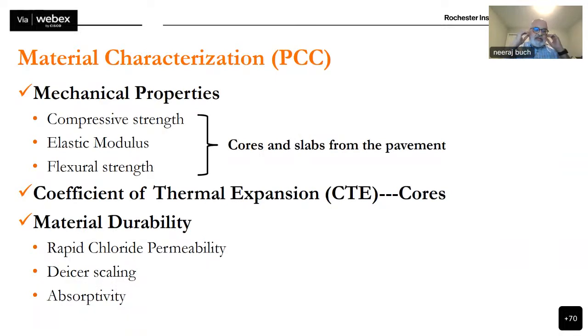So moving on to the material characterization, of course, there were a lot of tests done, and I don't have time to go through all the testing, but I've sort of picked some examples. So we looked at mechanical properties, and the three common mechanical properties that we looked at were the compressive strength, that was either based on cylinders or cores that were extracted from the concrete slabs, and then measured the elastic modulus on the cylinders or the cores, and then also flexural strength on beams. We also then measured and quantified the coefficient of thermal expansion of the concrete, and I'll explain why that is important.